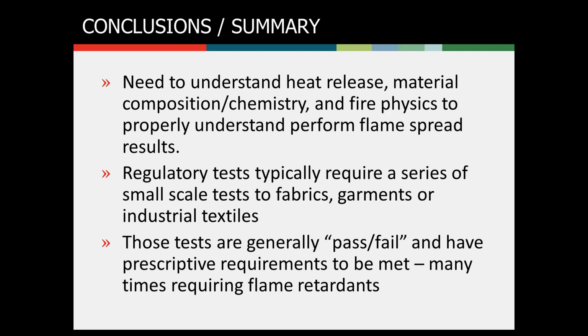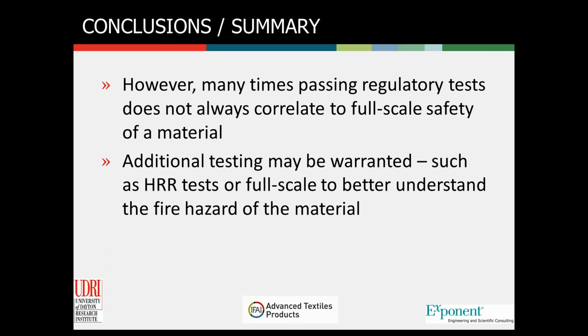Regulatory tests differ a good deal from heat release rate measurements and research-based testing. The regulatory tests are mostly small-scale tests on fabrics, garments, and textiles. They generally are only pass-fail, and in order to meet those requirements, you many times have to use flame retardants. But just because you pass a regulatory test, such as CFR 1610, the 45-degree angle test for apparel clothing, doesn't mean your material is going to perform well in everything. That's where additional testing and analysis, either heat release rate or full scale with a mannequin, can really come into play and give you a good idea of how your material is going to perform in a full-scale fire scenario.